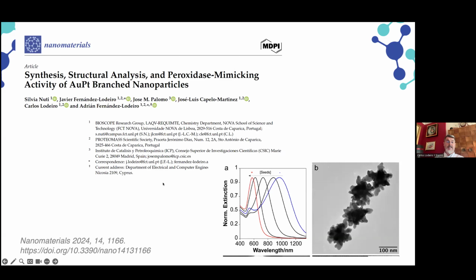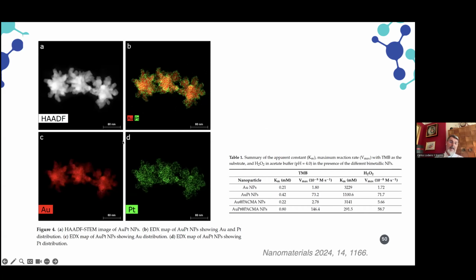We can apply the same technology. We can use the same molecules to stabilize these bimetallic nanoparticles. Here in panel B, you can see the shape of these anisotropic nanostars, or nano arms, with the platinum. And once again, we can control the deposition of the platinum around the external part and in the points of these nanostars. And inside, we have the gold connected to the core of the nanoparticles.